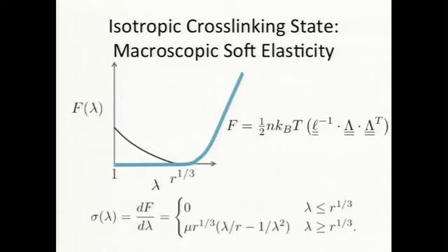Okay, so this is the energy if the microscopic deformation was really the same as the macroscopic deformation, and this is the energy after you allow the formation of the most favourable domain structure. Then this is energy against stretch. Clearly, if I take a derivative, I get stress, and this is stress-free. So you get a stress-free transition from macroscopically isotropic to macroscopically aligned.